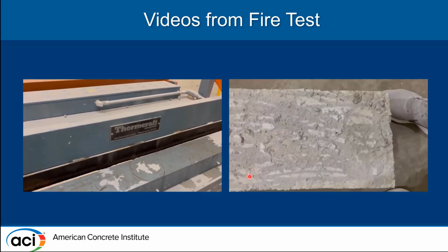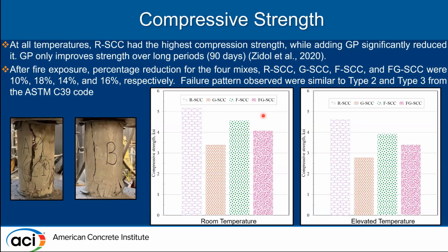My second video here represents the cracking. Basically, this video was added to show you the surface cracking that actually occurred due to the fire exposure of the specimens. Moving on to the results of these tests, beginning with the compressive strength, the maximum compressive strength observed at both the room temperature and after fire exposure, that's the elevated temperature, was highest for R-SCC and lowest for the glass pozzolan variant, that is the G-SCC.